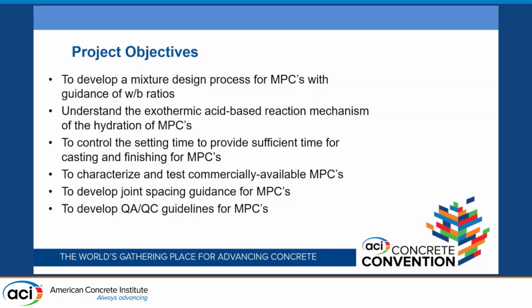Then we had to understand the exothermic acid-base reaction mechanism and control the setting time. It's very rapid setting. It's hard to place a parking apron if it's setting up in 20 minutes. So there's several ways you do that with MPCs. And then the rest of it is the constructability aspect: you want to develop joint spacing guidance. Can we do full depth repairs? Can we do partial depth repairs? When do we do doweling? All this other kind of stuff.